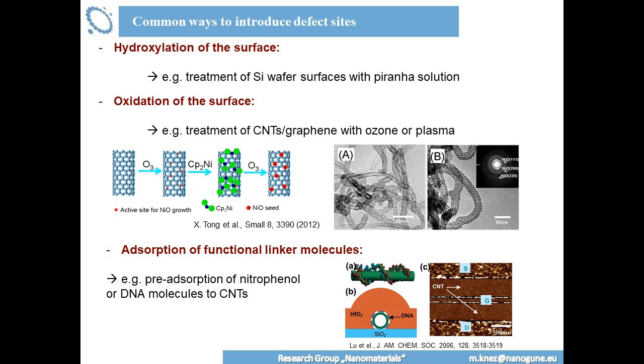Also, an initial approach was to treat silicon wafers with microcontact printing, so you can have, for example, self-assembled monolayers printed on top in line shapes and arrow shapes. And those parts will be either functional or non-functional, depending on your molecules. On those places you won't grow, so the precursors will stay away from there, but they will diffuse, and they will grow on those spots where you have functional sites. A bit complicated to understand, but if you have questions, we can talk about it later.